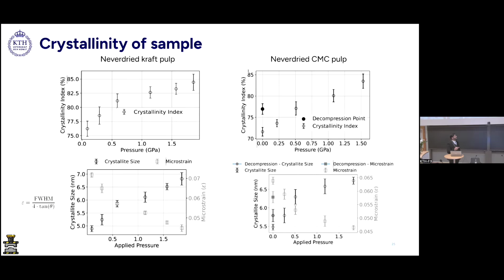Similar results were also seen in the never-dried carboxymethylated pulp, where we saw a steady increment in the crystallinity of the sample. For the decompression signal, we could see that the crystallinity was going down, but it did not go all the way down to its original value. It had some permanent deformations. Also, the crystallite size was getting bigger. Again, this could relate to co-crystallization, and the microstrain was going down, which is an indication of a more ordered structure.